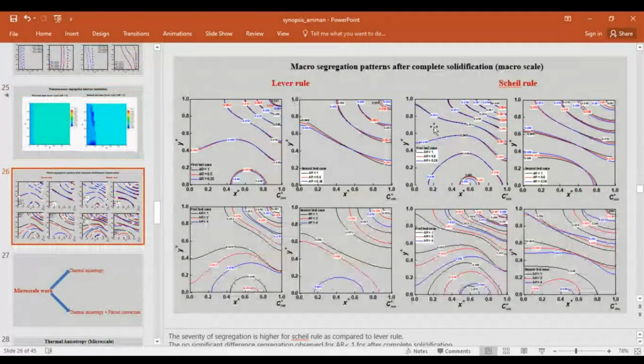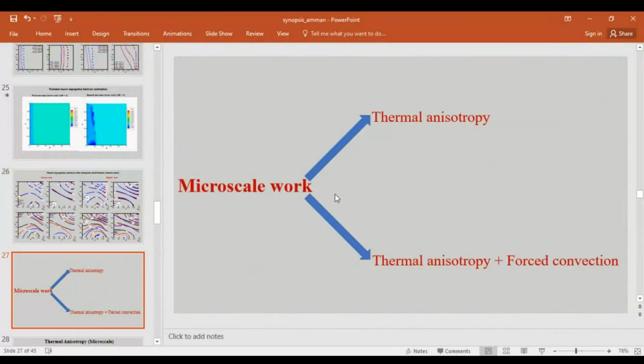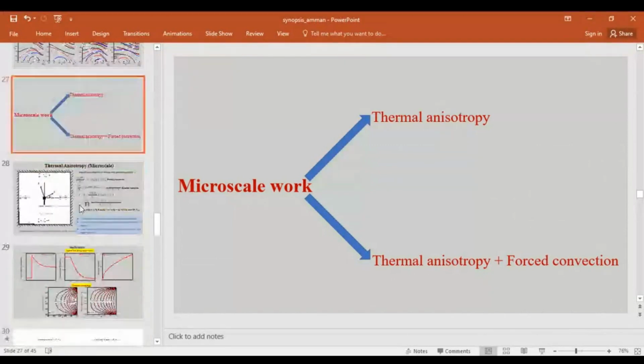Now moving on, this is the comparison between the Lever rule and Scheil model. Just the gist I'm telling you: with the increase in anisotropy ratio, the degree of segregation is less. So that has been observed, right? So this concludes our macro scale work. Next, moving on to micro scale work. The micro scale work can be divided into thermal anisotropy, and thermal anisotropy plus forced convection, right?